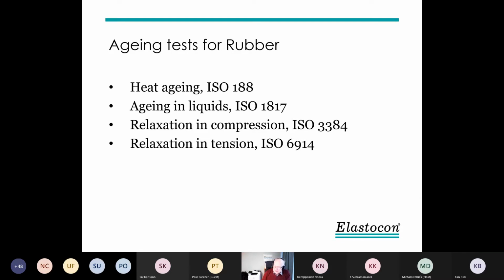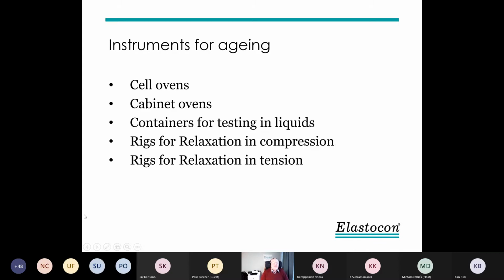So there is difference in the results between these two tests, mainly depending on the exposure for oxygen. What instruments are we using for aging? We use cell ovens, we use cabinet ovens, and we can use containers, testing liquids. And for relaxation, we have relaxation rigs, which can be equipped for testing in compression or testing in tension.